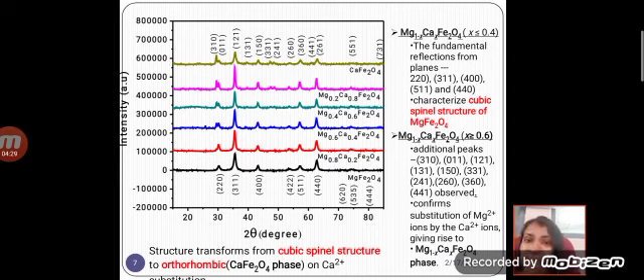And we can see that for doping of 60% calcium in magnesium ferrite nanocrystal, some additional peaks like 310, 011 and 121, etc., which correspond to the orthorhombic structure, start appearing in the XRD pattern. So after doping with above 60% calcium, the structure starts transforming from cubic to orthorhombic structure. This can be observed from this X-ray diffraction pattern.